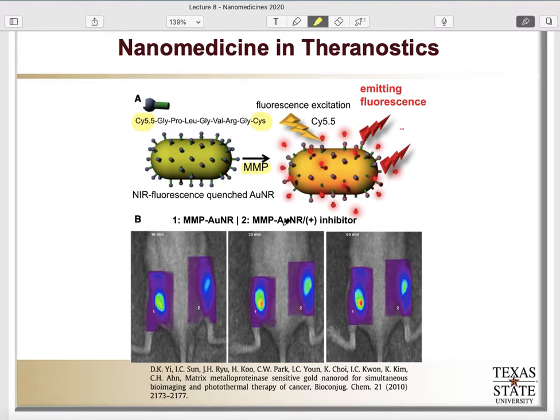Number two is the nanoparticles that have the fluorophore also that are in the presence of an inhibitor. And so what you can see is that in number one, in all cases, we have fluorescence development. On number two, we have an inhibitor of the enzyme, meaning that that cleavage process cannot occur as readily, and we can see significantly lower fluorescence development. So that's a proof of concept just to show that, in fact, the fluorescence that we're seeing is from the development of, or from the activation through the function of the enzymes.